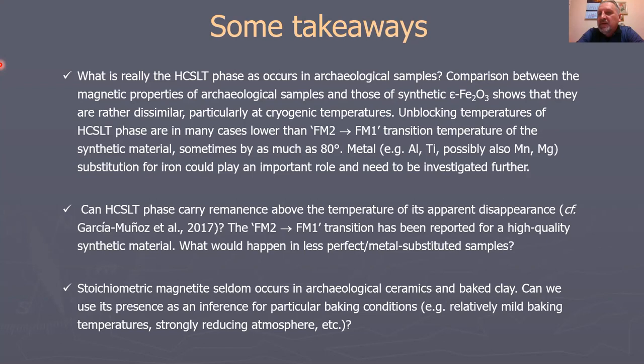Well, there was recently the same Spanish group that I mentioned that published a paper where they tried to do the Thellier experiment on a highly perfect synthetic sample. This is Lopez Sanchez and others 2020, but unfortunately the powder was dispersed in epoxy, which could not be heated above 235 degrees centigrade. So we still don't know what would happen in a highly perfect sample. We still don't know what would happen in a sample like our red material. It's something that we have in mind to try.